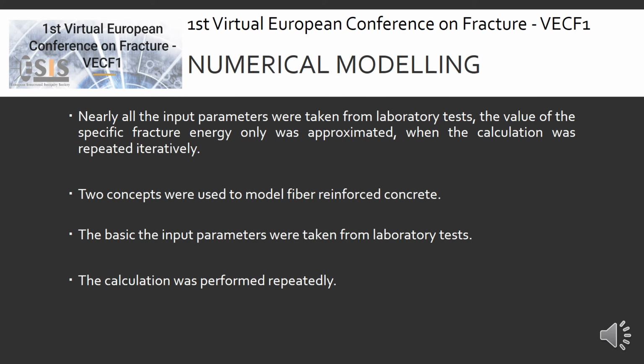Nearly all the input parameters were taken from laboratory tests. Only the value of the specific fracture energy was approximated when the calculation was repeated iteratively. Two concepts were used to model fiber reinforced concrete. The first concept, for fiber dosing 40 kg per cubic meter, is based on the use of effective values of tensile strength and fracture energy. The second concept, for fiber dosing 75 and 110 kg per cubic meter, is based on the actual modeling of the concrete matrix and fiber reinforcement.